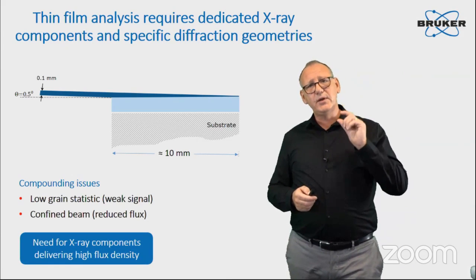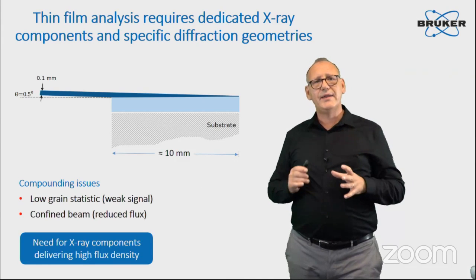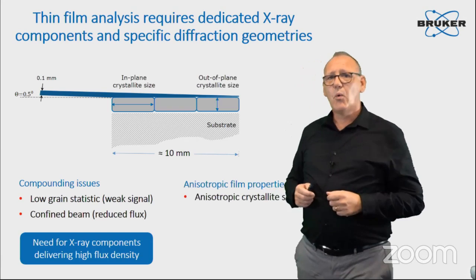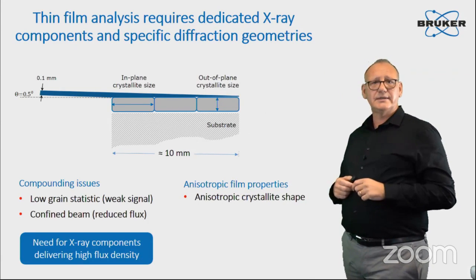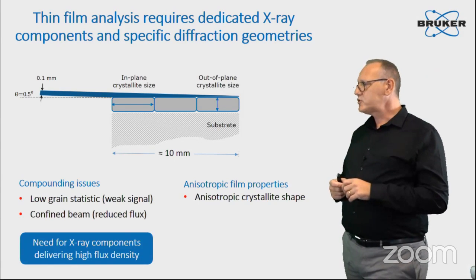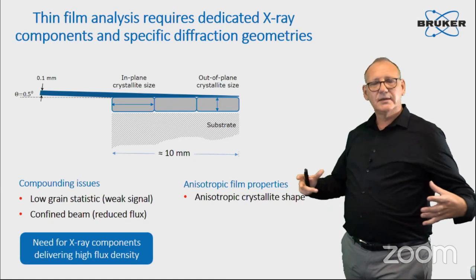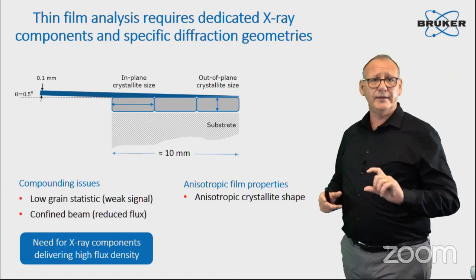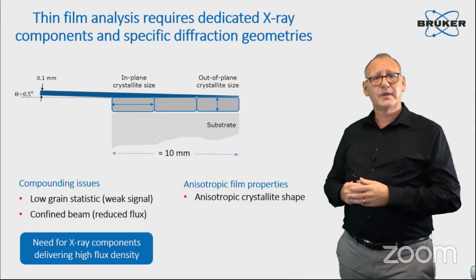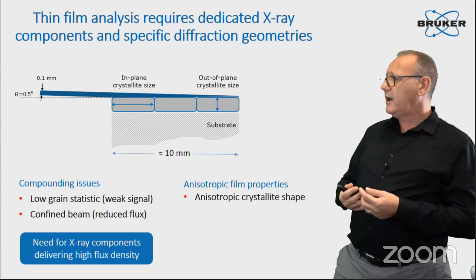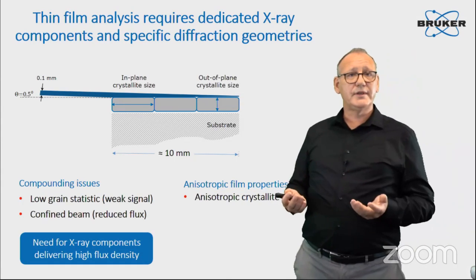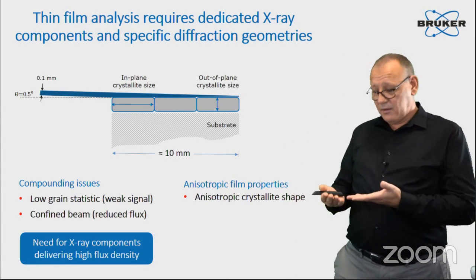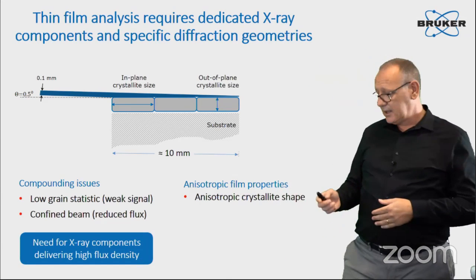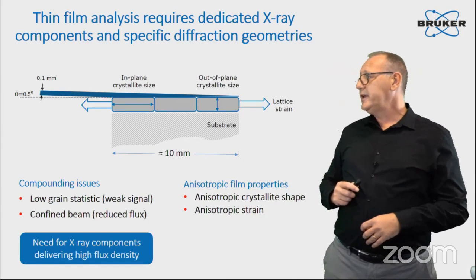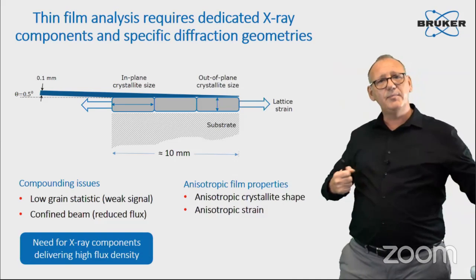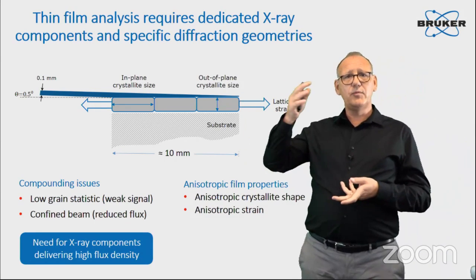Another property of the thin film: the thinner you go with the film thickness, the more anisotropic properties you will have in your material. One of them could be, for example, the anisotropic crystallite size. If you reduce the film to a few nanometers, most probably the in-plane crystallite size might grow broader than the out-of-plane, which will anyhow not be thicker than the layer thickness. So the question is, how can I investigate those properties in different directions while keeping my grazing incidence beam? Another parameter you may be able to extract is the lattice strain, and this mostly acts in the plane. So again, I have to measure information out of the plane and in the plane.